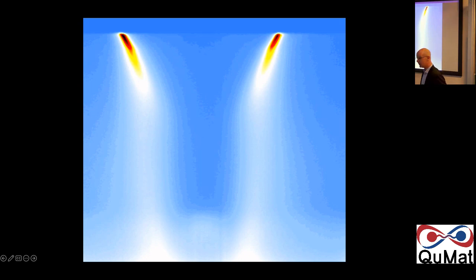So here we see we're going from one Brillouin zone diagonal to the other. The gamma point is in the middle. This band is somewhere down here. And then we're crossing the Fermi energy up here. So from this central point, where my laser spot is, from here to here, is KF. Okay. And this is KF in the other direction. So we have 2 symmetric bands. We're very careful to align our sample as perfectly as possible to get these things as equal as possible. That gives us one single pixel of information for our story.